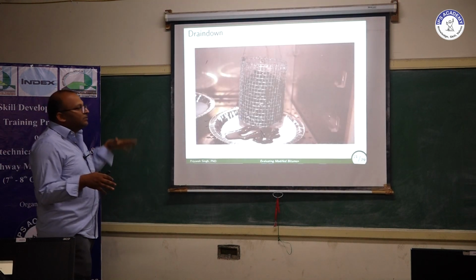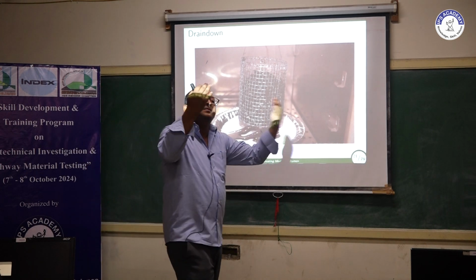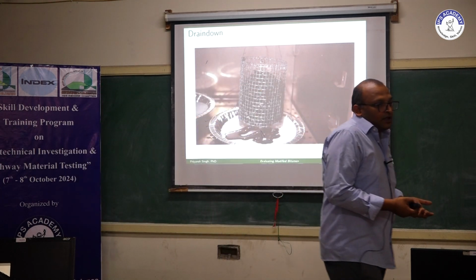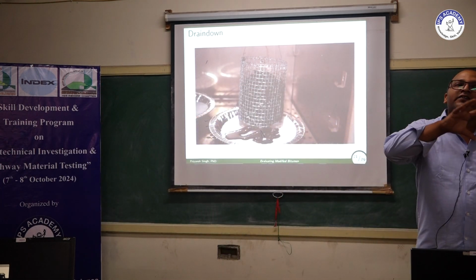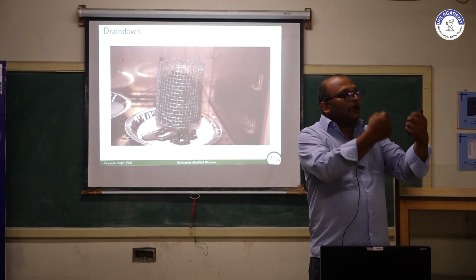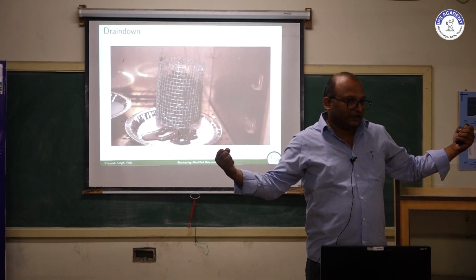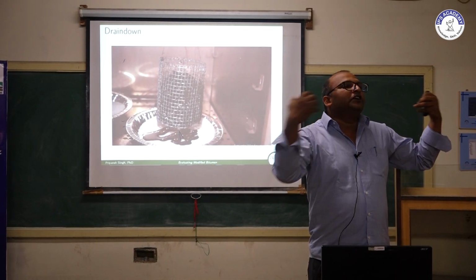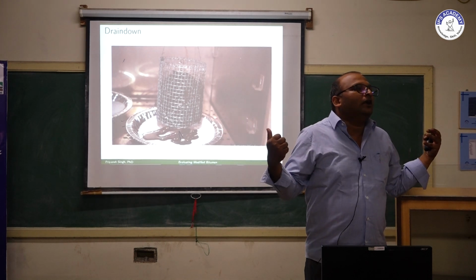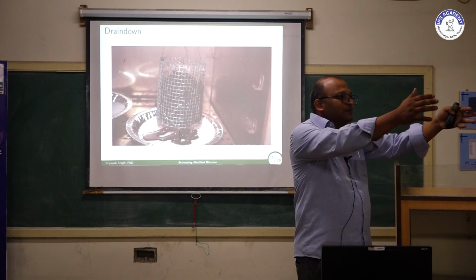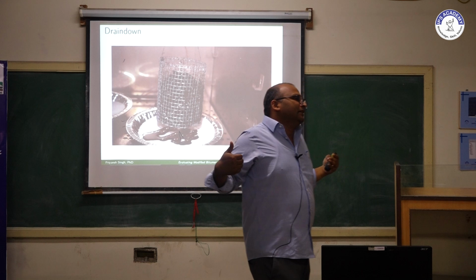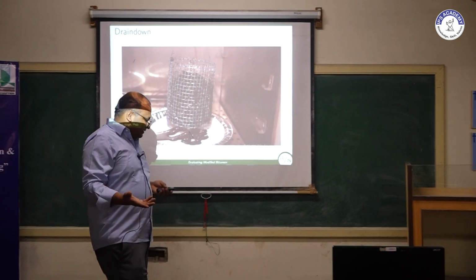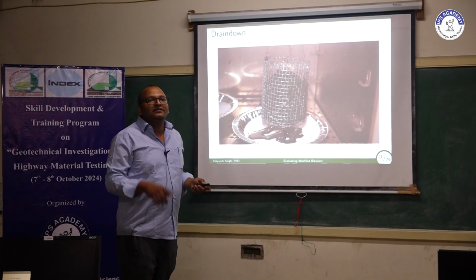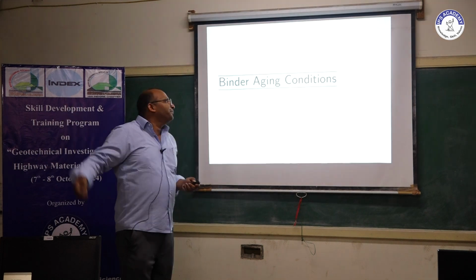So the first test I am discussing is at the high temperature, which is drain down. Now whenever you are mixing your binder with aggregate, the binder and aggregate should not separate from each other. If they are separating from each other, it is called drain down. That means if you put your mix, binder will separate out. That should not happen. This test is related with mixing temperature.